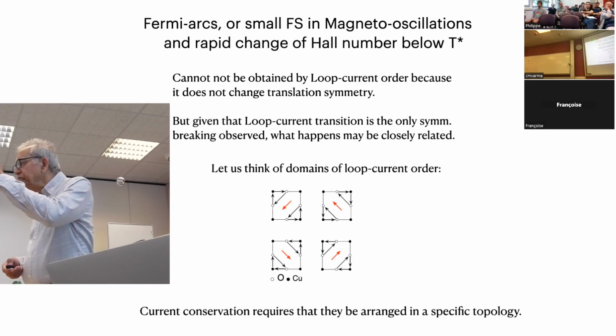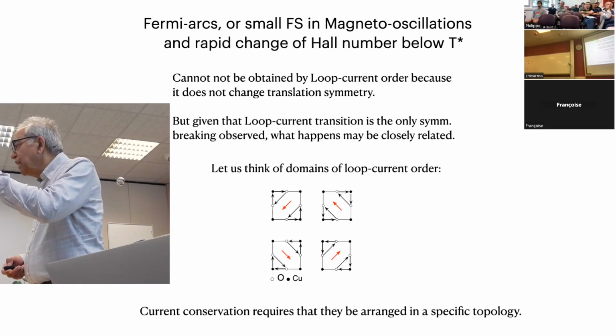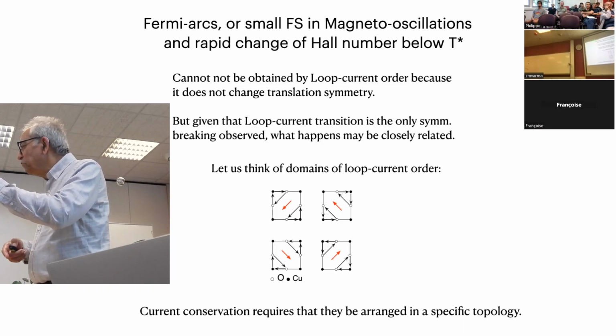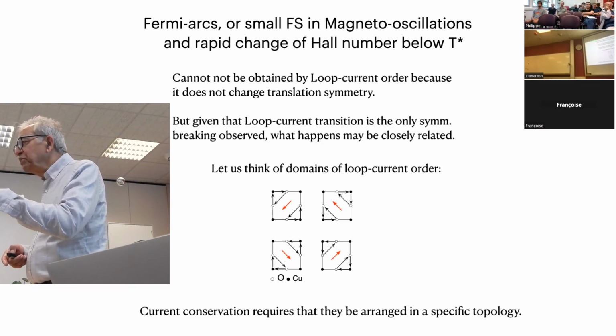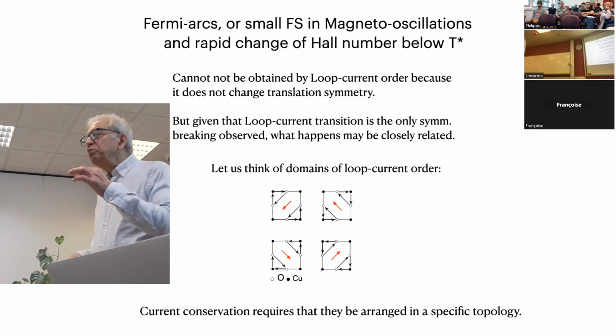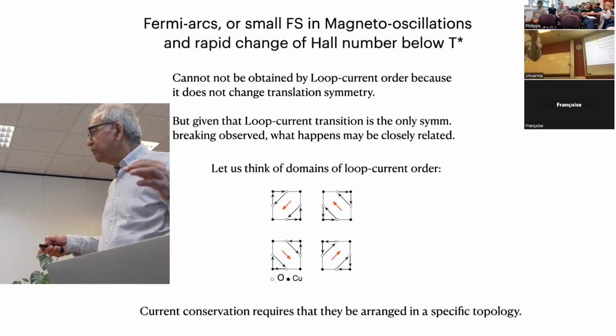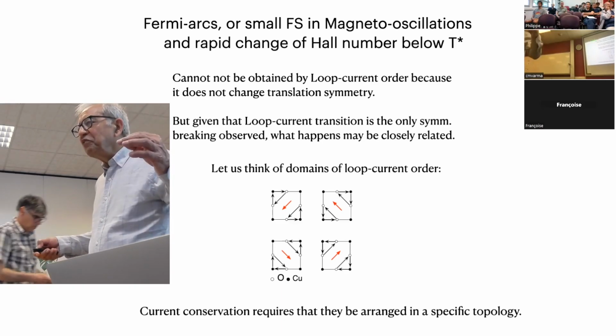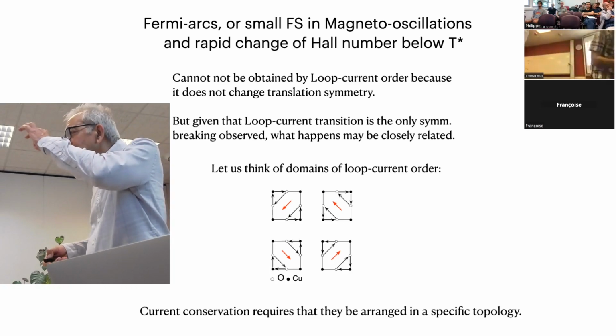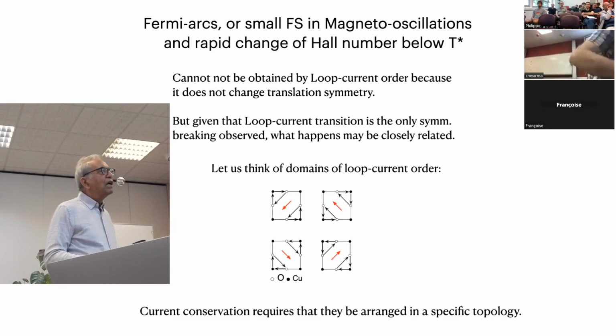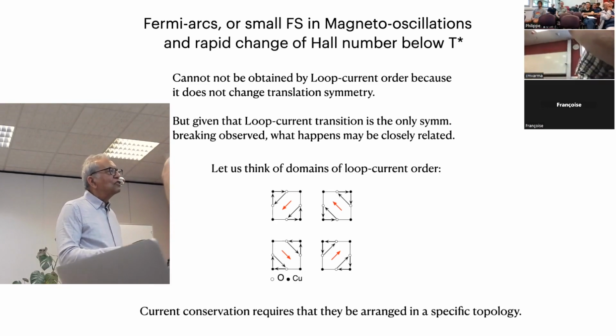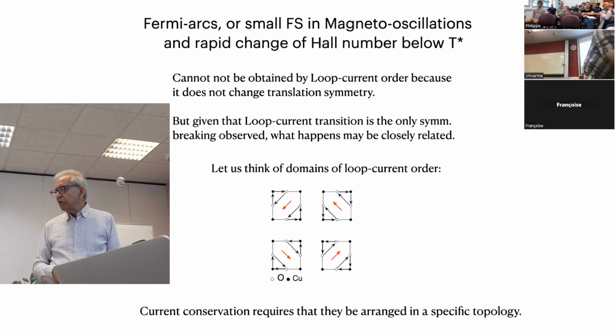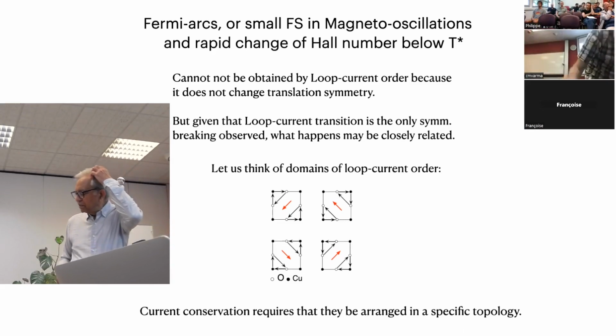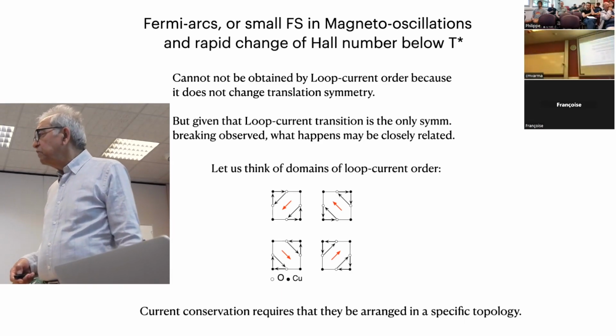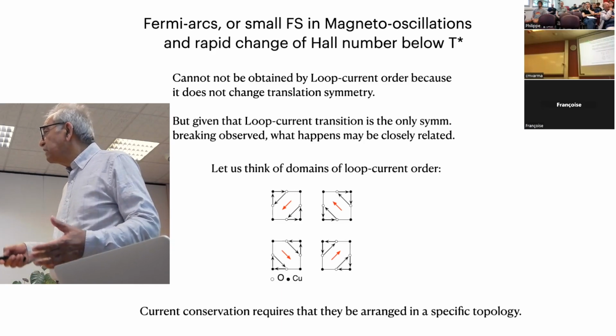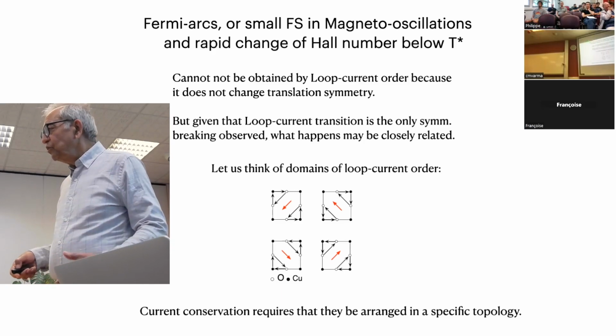Now, that closed Fermi surface, there may be a few of them, and they are degenerate, what you measure is 2% of the Brillouin zone, whereas the whole Fermi surface is more like 50% of the Brillouin zone. So you see 2%. You see a tiny pocket. Okay? And so one has to think of something, and this has been for me the hardest thing, because I'm always thinking of very complicated things, okay, for the pseudogap phase.